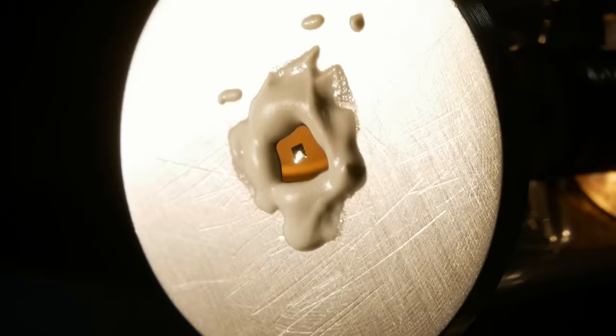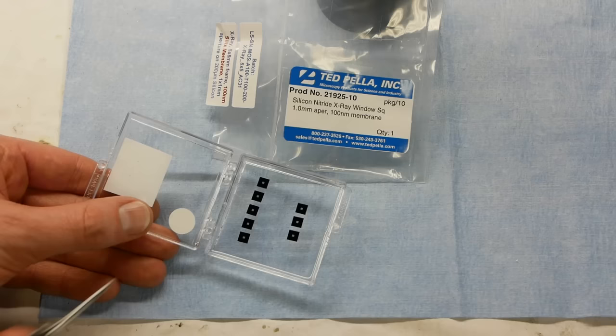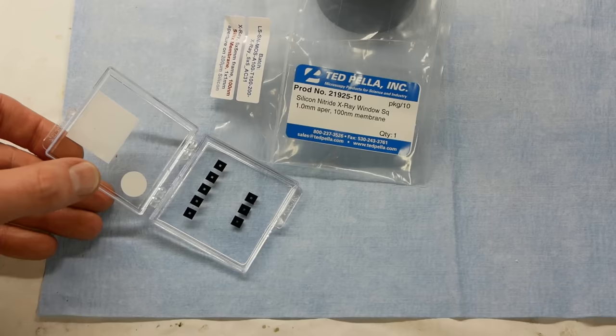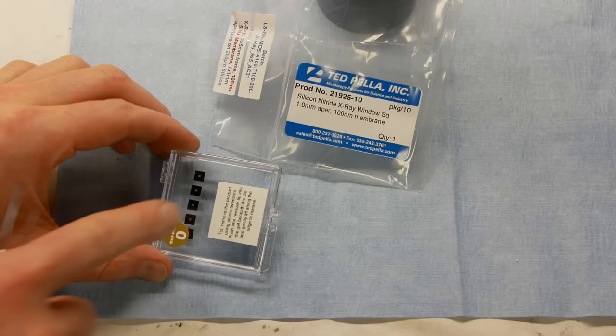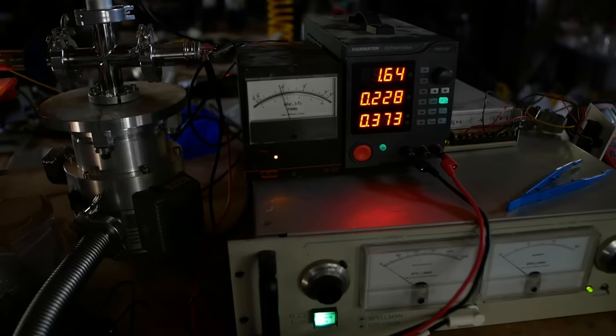Although you can see I only have eight left, so I actually did destroy one of these, unfortunately not on camera, but it wasn't that spectacular of a failure anyway. I started the voltage before I was fully pumped down, and there was a plasma formed in the tube. For some reason, the plasma caused the window to pop and I lost vacuum. So I did learn that exposing the turbo molecular pump to air, at least through a 1x1 millimeter aperture, does not kill it. So that's an existence proof that doing that does not mean instant death for your turbo, although it's probably not good for it in the long term.